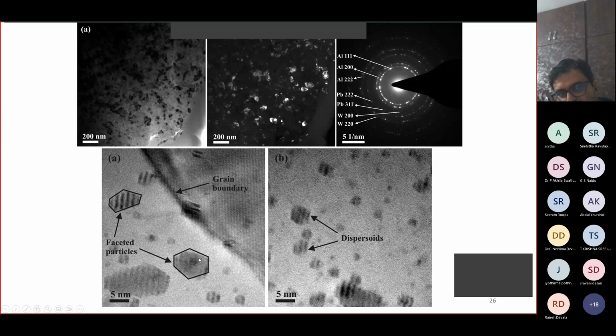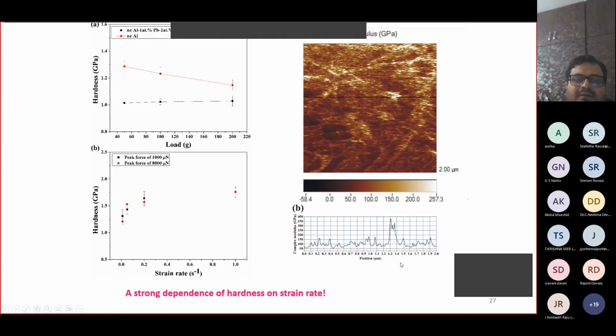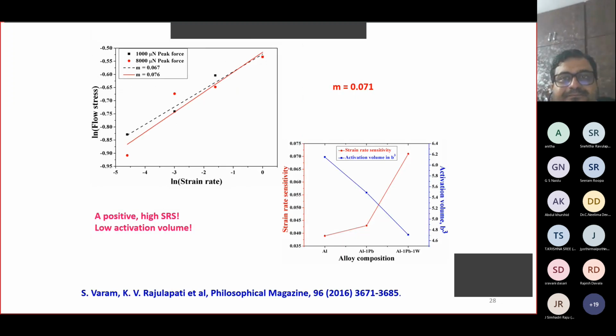And further, you see small particles here which are faceted in nature. They are faceted particles. And also when we try to understand the variation of hardness and strain rate, there is a strong dependence of hardness. That means when you vary the strain rate, hardness also increases. Hardness and flow stress are directly related in a sense using some kind of constraint factor proposed by the scientist called Tabor, that is Vickers hardness by 3 roughly gives you the yield strength and flow stress of your material.